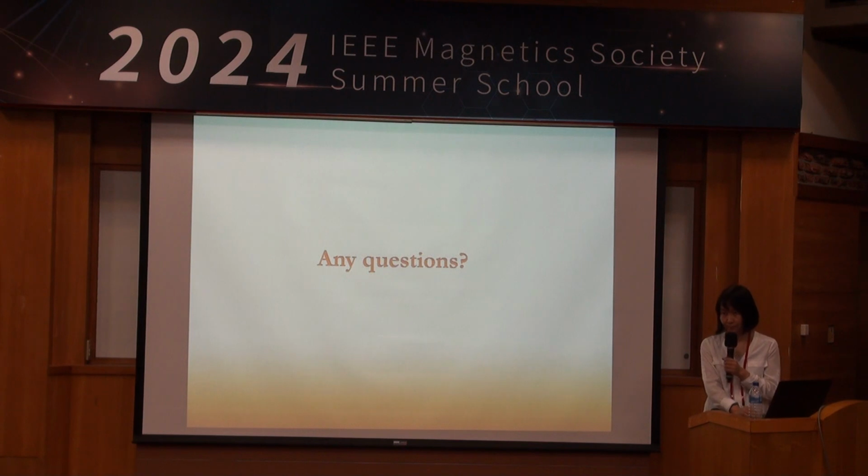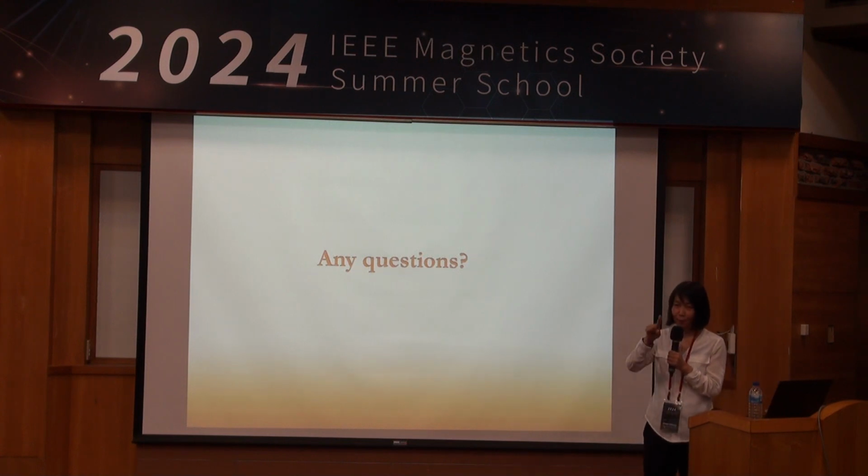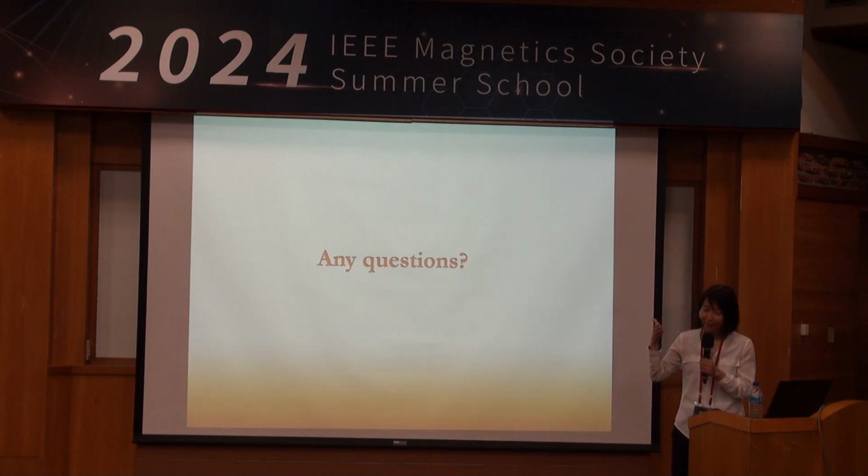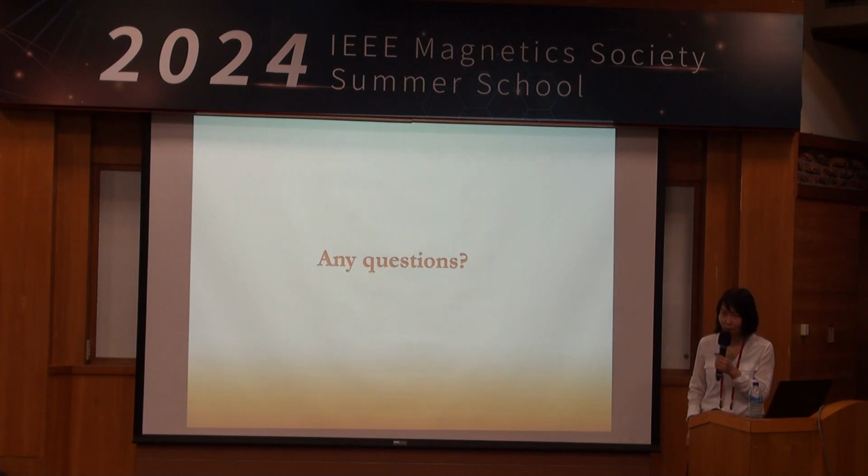And I want to ask, why do we always have to apply a certain amount of external field to define the propagation direction of magnetism? Right. So, you know, a magnon is a small precession around a saturation magnetization. So actually, magnon, I'll cover that later on, depends on... I think a magnon without a saturated moment is ill-defined. So typically you need to establish a saturation magnetization, and then depending on the propagation direction of the magnon relative to the saturation magnetization, the dispersion can be very different. Okay, so this is how people work with a well-defined magnon mode.